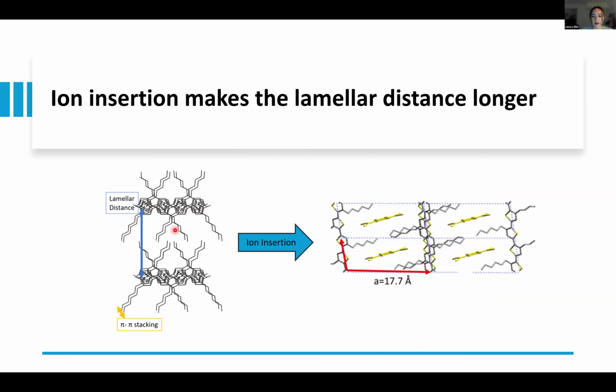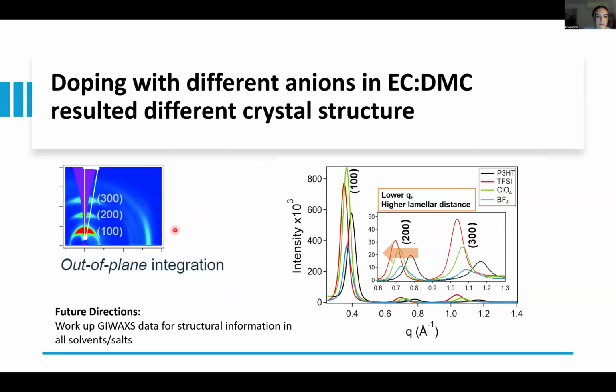So we expect that upon ion insertion, we're going to get a greater lamellar distance, which is going to correspond to a lower Q value. So in order to look at the lamellar distance, we can integrate this region right here at various radius values and get this plot on the right. And so Q is inversely proportional to D. So as the plots shift left, this is indicating an increase in the D spacing.